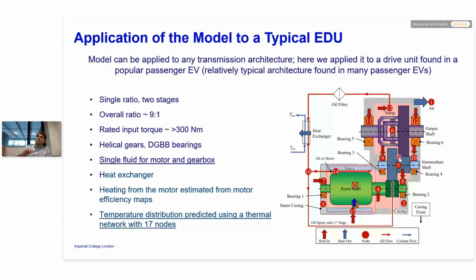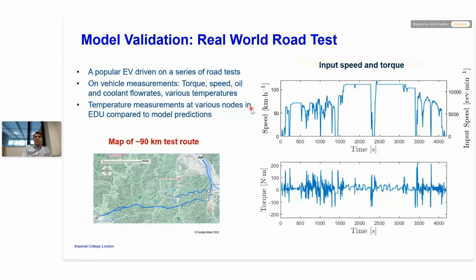And to address this temperature evolution and interaction of the losses, what we implemented is a thermal network model. These numbers are the nodes of our thermal network. We work out the losses at each of these points, bearings, gear meshes, and the churning, and the heat exchanges at each point, including in the motor, because of the cooling of the motor, in the heat exchanger, between the gears and so on. Then we allow them to talk to each other to get the overall evolution of temperature as the car is being driven. What Joe and Alex then did is drive that specific vehicle through this route, and the car was instrumented with lots of thermocouples in the transmission.